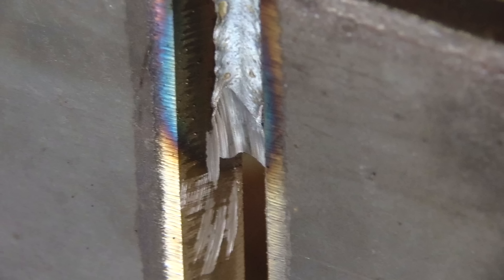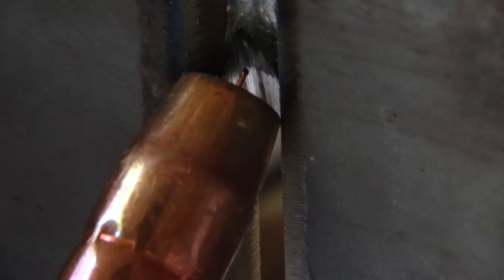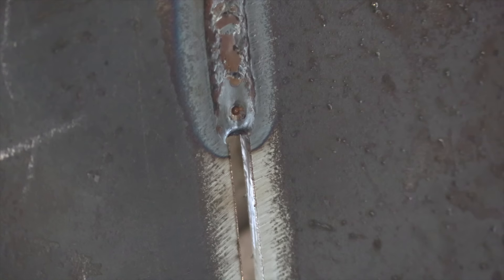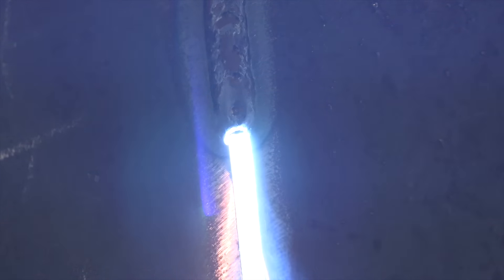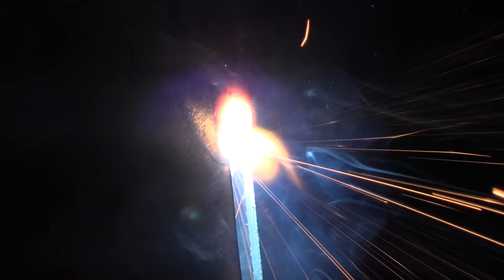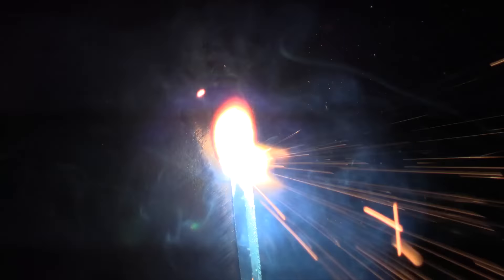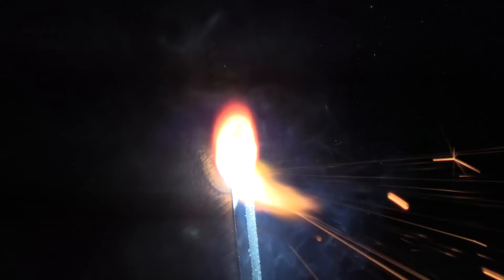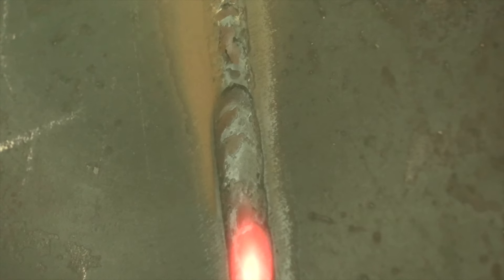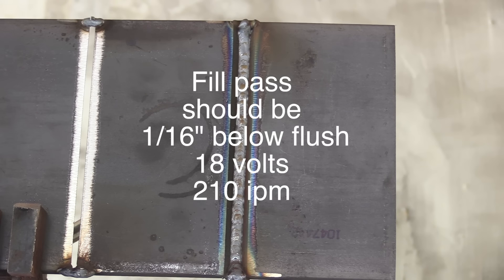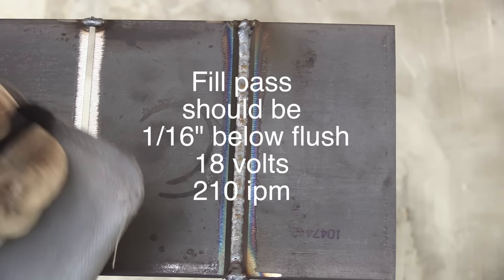It wouldn't hurt a thing if I tapered this back another quarter of an inch to give myself a nice launching pad. But here's the back side of it. You can see it warming up, gives it a chance to warm up before it consumes that thinnest part of it. And then if you taper it back far enough, you will have a nice smooth tie-in. You'll hardly be able to tell.